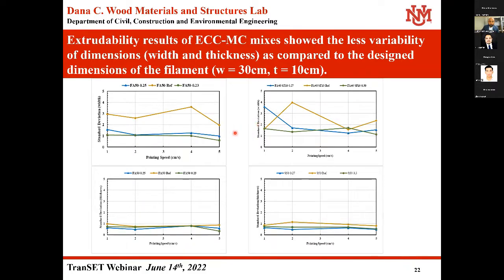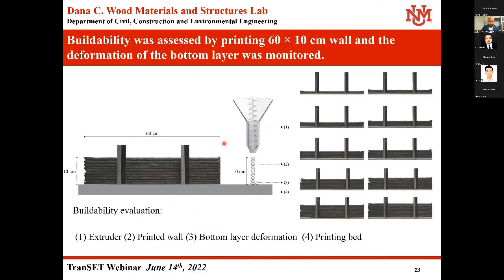We see the variability in the dimension with the standard deviation. As you can see, the reference mix has more variability in the dimension. That's showing it has less conformity of the dimension. But when we add the MC, viscosity modifier, in the mix, the variability in the dimension over the length of the filament was considerably reduced as compared to the reference mix.